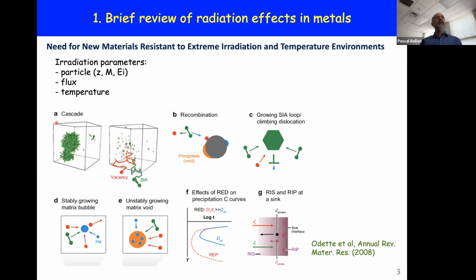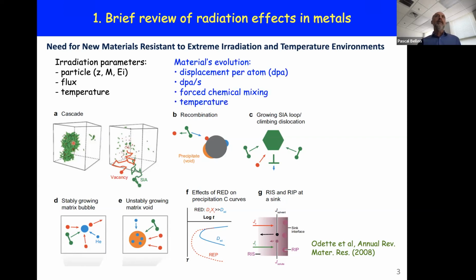But here we're concerned with metallic materials, and so this energetic particle will start first by exciting the electronic system of the atoms in the target, but these excitations do not lead to any defect. It is in the second phase, during which the incoming particle undergoes nuclear interactions, or interactions with the nuclei of the atoms in the target, that damage can be produced. That damage takes place typically by the formation of so-called displacement cascades, which extend over a few nanometers, last a few picoseconds, and result in the formation of Frenkel pairs, that is, a vacancy and an interstitial.